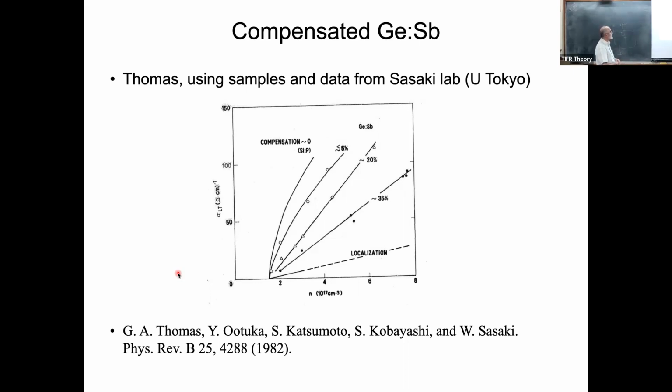And what he found was that as antimony doped germanium became more and more compensated, the square root type behavior started becoming linear. So this is an experimental observation that uncompensated systems seem to have a more abrupt onset with a smaller exponent than compensated systems, which seem to have a linear onset. And today, that's about the only reliable result there is.